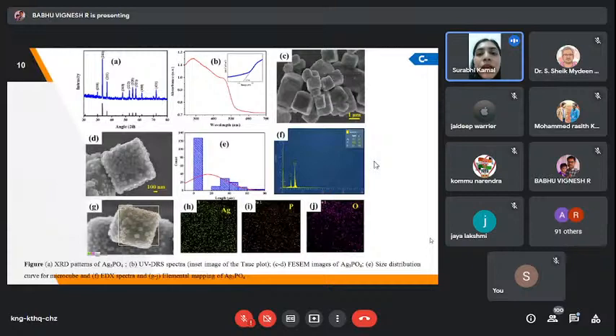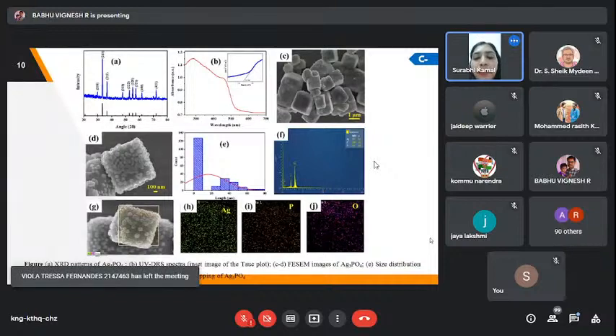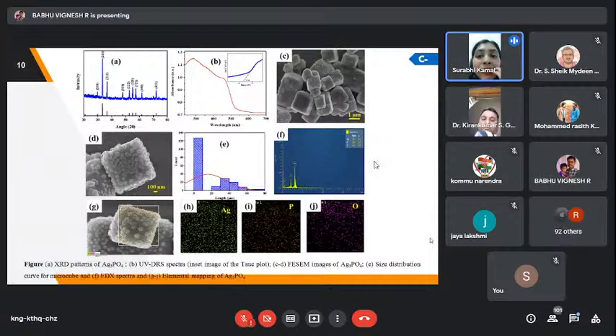In this slide, you can see that I had taken the XRD of the Ag phosphate, the UV-DRS, as well as the FESEM. You can see there is a microcube formation. The goal of this paper was to make rough surface cubes. That is why it is a rough surface, and the Ag is sitting onto the silver phosphate surface. We had taken the SEM, calculated the size distribution curve, and EDAX as well as the elemental mapping for this silver phosphate.